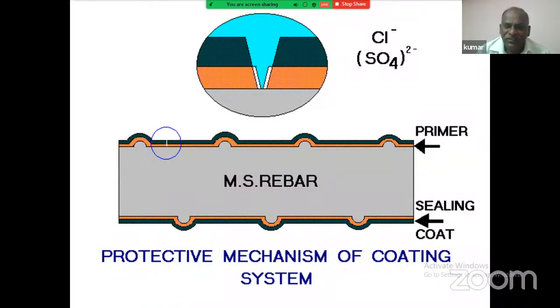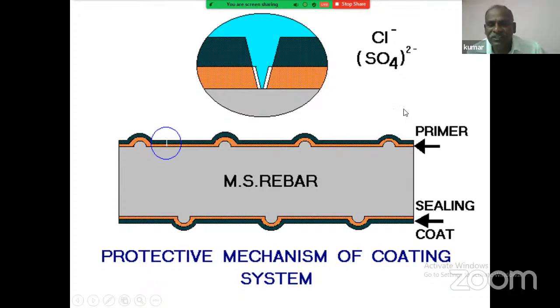Suppose, for example, while you are pouring concrete, we cannot avoid pinholes. So when a pinhole is created, the primer is hydrophobic in nature. Whatever Cl minus, these are the vulnerable things which create corrosion if they come in. Because of hydrophobicity, it makes a repulsive action. It cannot come in. So this is the mechanism provided here, such that Cl minus and SO4 cannot reach the surface of the steel. Even if it is hydrophobic, automatically this will also not come in. It will be repulsive. So that is the corrosion protection mechanism.